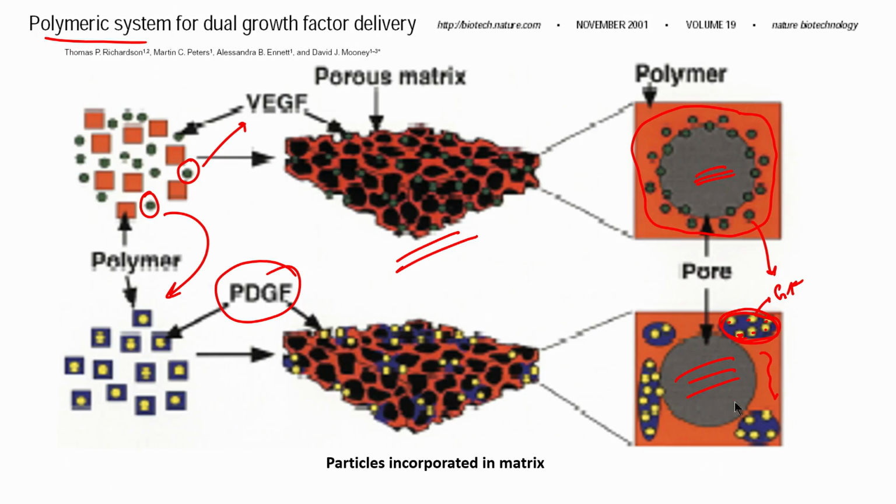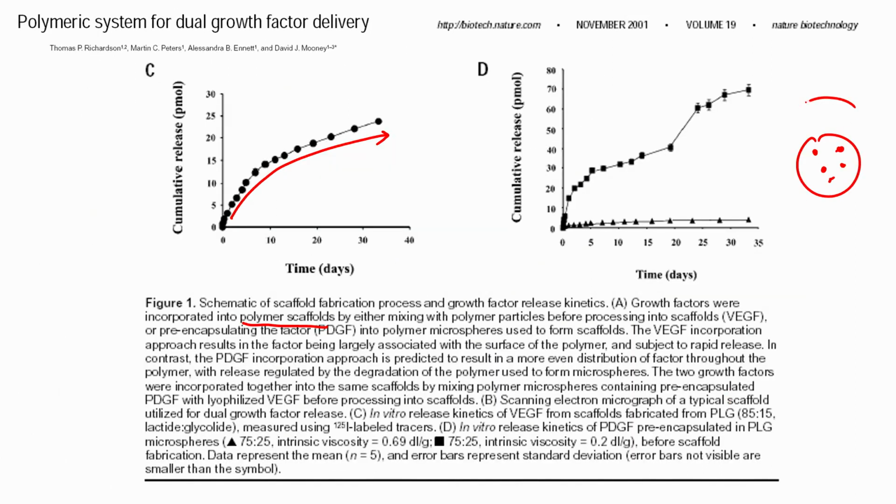and when they have done that, this whole polymer then gets encapsulated into another polymer which contains pores through which these can diffuse out. So, now the growth factor first has to wait for this matrix to degrade and then they can start to diffuse out. So, you see a much longer release and sort of a biphasic release in this particular example. So, this is just some of the ways these authors have tried to change the release of their molecule through these matrices.